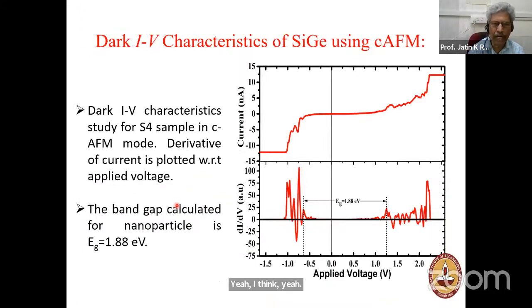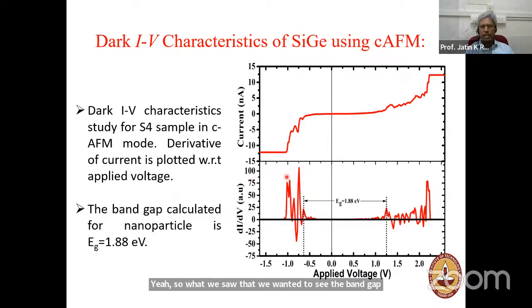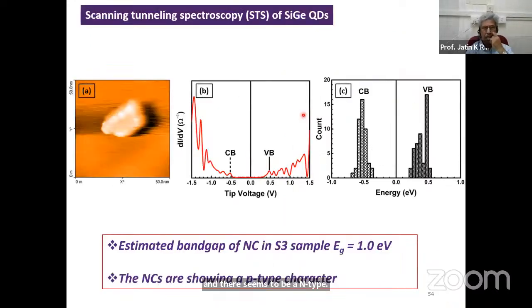So we wanted to see the band gap of this material, the silicon germanium quantum dots. If we use conducting AFM and find out the current and voltage, we found the band gap to be around 1.8 electron volt, and this seems to be n-type. However, if you use scanning tunneling microscopy, we found that it's more of a slightly p-type, and the band gap is around 1 electron volt for this one particular type of material.